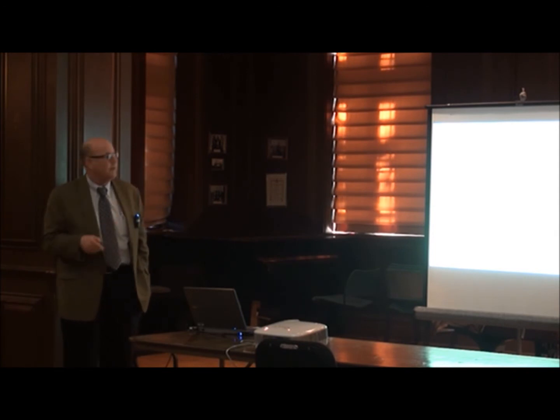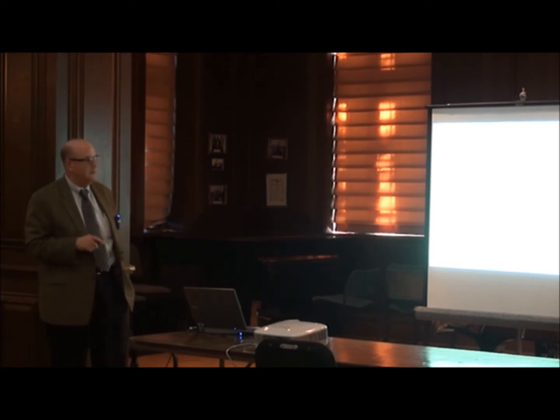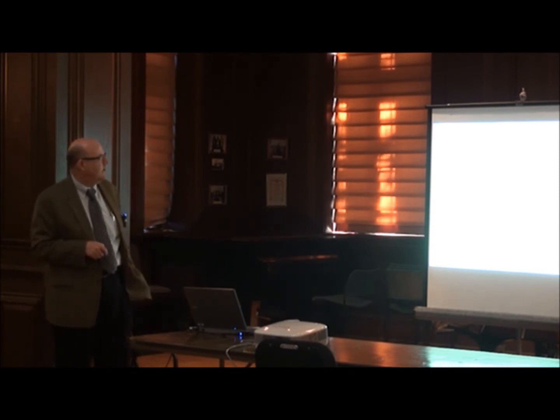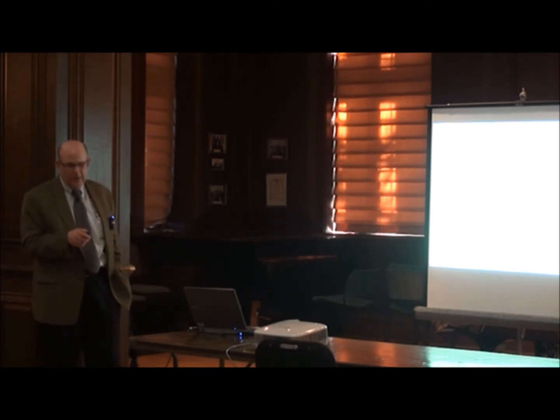So what we talk in terms of is a relationship or a curve that's known in the tribology literature called the Stribeck curve. And what we're plotting here is this friction coefficient. So remember, it's friction coefficient. For another time, we can talk about the subtle difference between that and plotting frictional force. As a function of basically a parameter that involves the viscosity, the speed, and the load that's exerted between the two components. Let's just think in terms of holding the viscosity and the load the same and just increasing the speed. What happens? As you go faster and faster and you move out to this side of the curve, you basically are entraining more and more fluid. The film thickness gets larger and you get lambdas much, much greater than 6. So the surface texture has minimal effect at that point on the friction. As we move down this curve and we start to slow down, we start to get to a spot where this lambda ratio falls between 3 and 6.